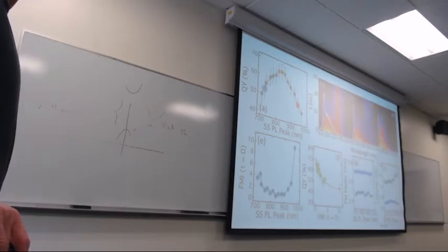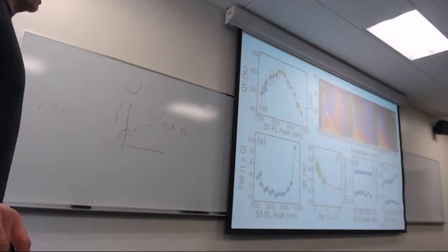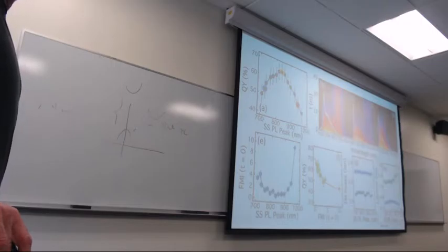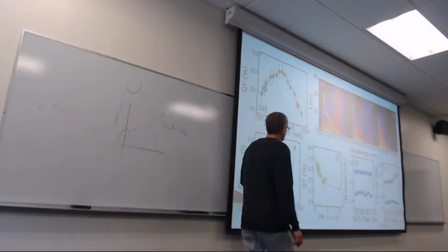But it's still possible to have hydrogen on the surface, right? Oh yes, there's most definitely hydrogen. That's what the plasma does. It passivates it initially with hydrogen, and then we go in and put the hydrocarbon chain on instead.